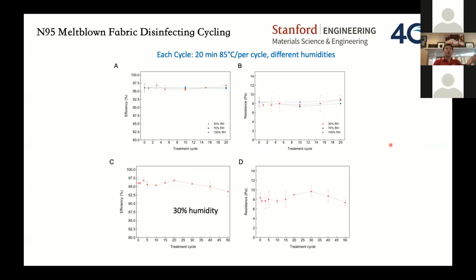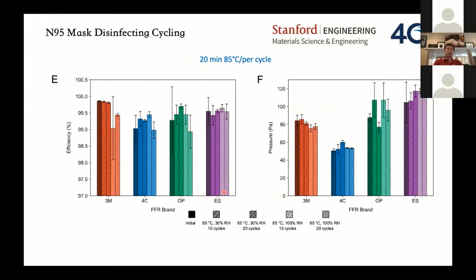Then we look further. One temperature, 85 degrees Celsius, 20 minutes per cycle, A and B under different humidity. You can go to 100% humidity. They are still working, the filtration efficiency doesn't drop. And for a dry heat condition, 30% humidity, we can run 50 cycles of treatment. And they still look like pretty high filtration efficiency. So this is the meltblown fabric level, which leads us to look into the mask level.